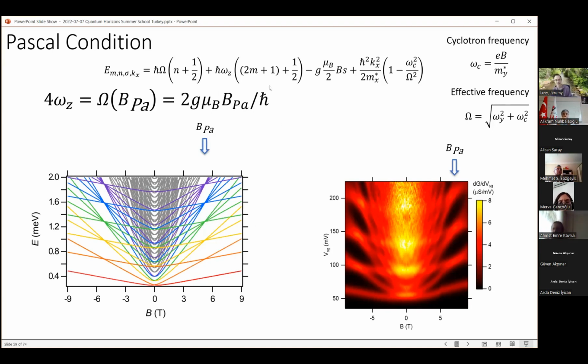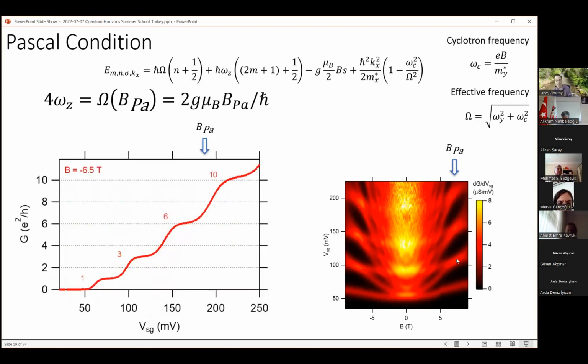And that happens basically with one experimental parameter that you need to have in the material, and one parameter that comes from the magnetic field. So we're able to observe, in fact, a situation in which you have the crossing of 2 and 3 and 4 and so forth. And then you need to add something else, which is the attractive electron-electron interactions. And when that happens, these crossings turn into strips that have a finite width. And so what you're seeing here are these lines that are actually coming together and staying together over a range of magnetic fields. So those are stable states.